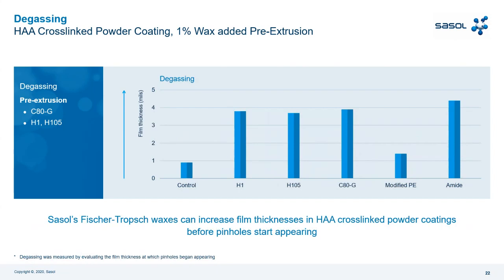Then we have the degassing. With HAA cross-linked powder coating, you can have degassing, and with 1% of wax in pre-extrusion, you can see the control that has a very low value, so means high degassing. You need to check the highest value. In pre-extrusion, you can see that Sasol wax C80G or Sasol wax H1 or Sasol wax H105, more or less, they give you similar degassing, so high degassing, respect to the control, and a modified PE, in this case HDPE, is quite similar to the control, so not so much help for the degassing, and amide wax give a high value. But these tests show you that also Fischer-Tropsch from Sasol help not only for other performance, but help also the system for the degassing in pre-extrusion.